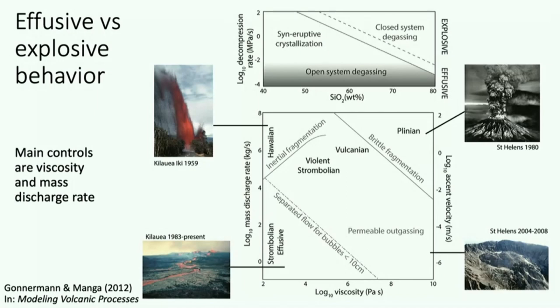Which means that if you have a basalt, you can form lava flows. You can also form lava fountains, which is actually breaking up into little particles there. Both of those are relatively low energy eruptions. And then for silicic lavas that are much more viscous and sticky, you can have an explosive Plinian eruption if there's a high mass discharge rate, but if things seep out of the ground slowly, you can form lava domes. So Mount St. Helens, and two different modes of eruption right there.